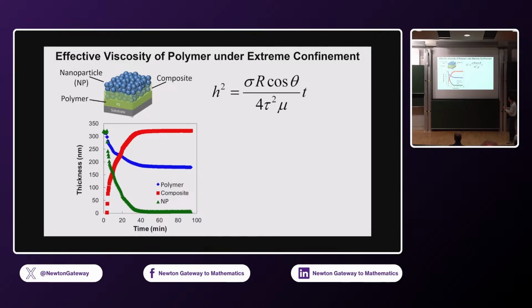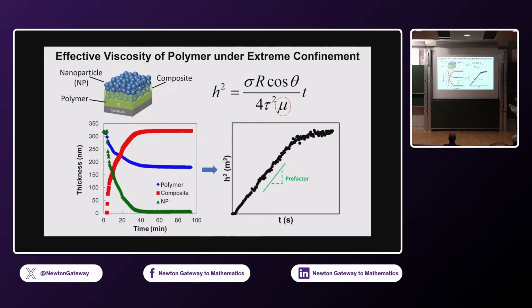As you can see, the composite layer goes from 0 to some thickness, and the nanoparticle and polymer layer thicknesses go down. What you'll see is that if you add this red curve and the green curve, it's more or less constant, right? Again, showing that this particle layer does not swell. It stays constant, meaning that you retain the original volume fraction and structure of that particle layer. And after we do this, we use the Lucas-Washburn equation to relate the height change as a function of time. By plotting this red curve as h squared versus t, we can get this prefactor. Now, we can make some assumptions about the surface tension, pore size, and contact angle of the polymer on the particle surface, which we now directly measure. Okay, we can infer what the effective viscosity of this polymer going through these pores is.